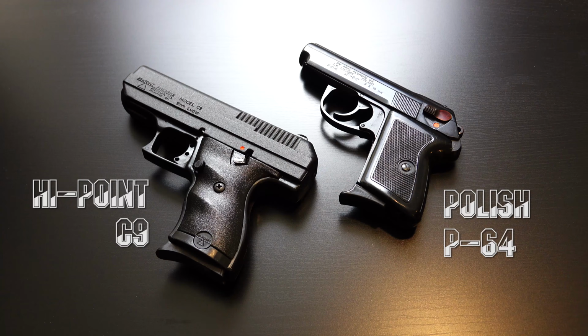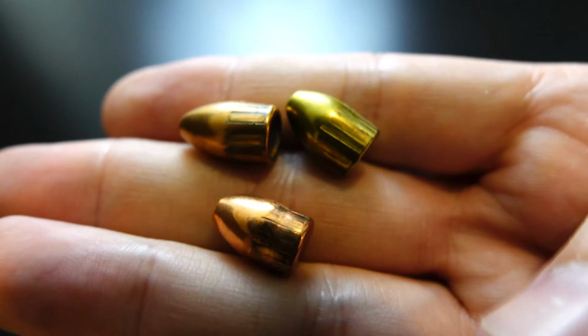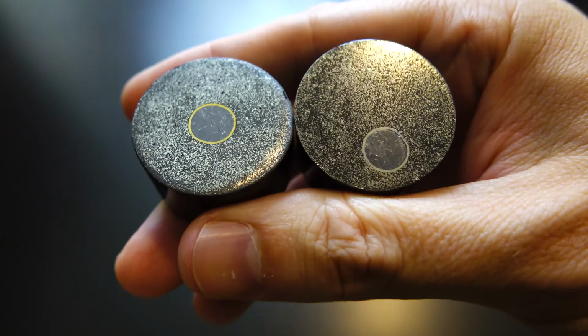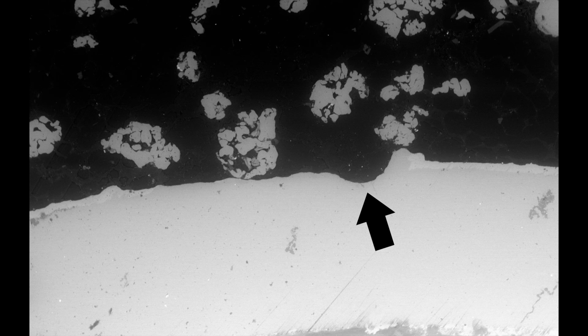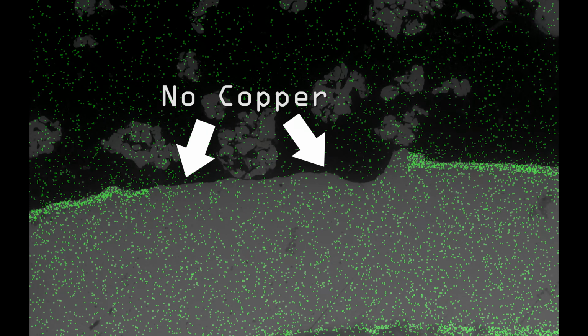I took some guns to the range and fired some bimetal ammo into some wet newspaper, which allowed me to recover the bullets intact. I then cut those in half, polished them, and put them in a microscope to see what we could see. So here we can see the indentations left by the rifling of the gun's barrel, and very clearly we can see the copper layer is gone and the land part of the rifling was digging into the steel.